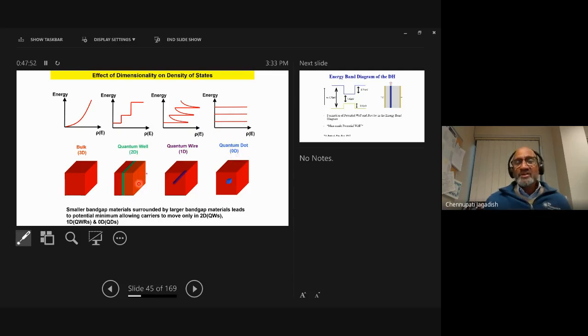So in fact, most of the current optoelectronic devices are making use of quantum wells, and some of the devices are making use of quantum wires and also quantum dots. Particularly quantum dots have got a much higher thermal stability and also much higher modulation speed. That means you can switch them on and off faster for higher frequencies. So that's why quantum dot lasers are coming into the market, which is quite significant. For example, we and others have really worked in this area.